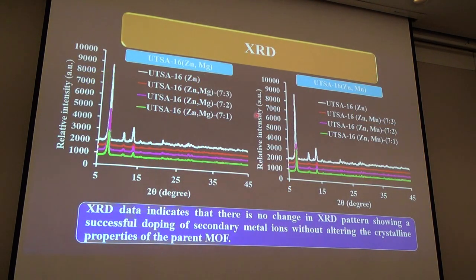XRD pattern. These are the XRD diagrams for the bimetallic MOFs UTSA-16 zinc Mg and UTSA-16 zinc Mn. The results show that there is no change in the XRD pattern after doping the secondary metal ion. That indicates the successful doping of the secondary metal ion without altering the crystalline properties.